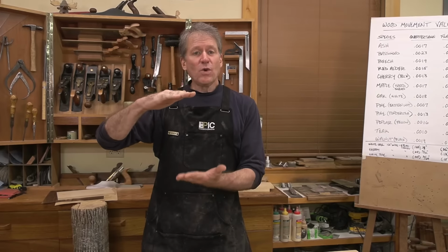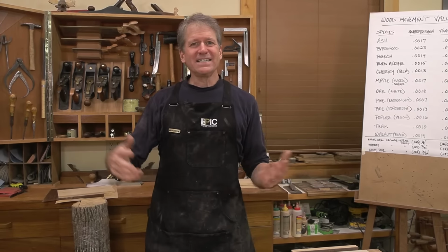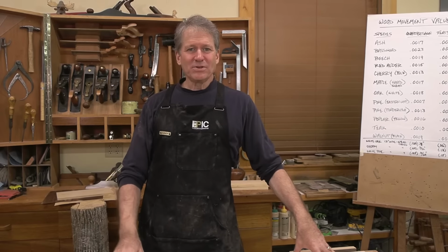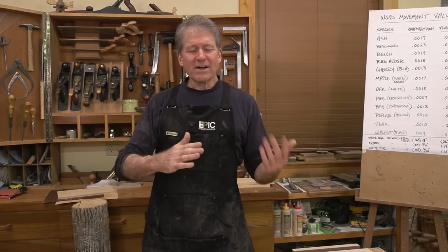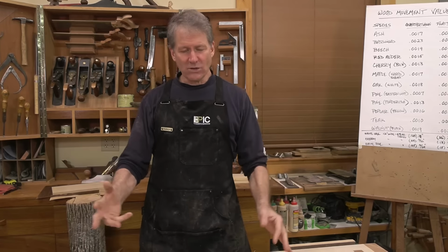So just think of if it's 35% moisture content, like I said earlier, you want to get it down to about 6 to 10%, or 8, around there is ideal for woodworking. Right around 6 to 8% is what it's typically kiln dried down to.